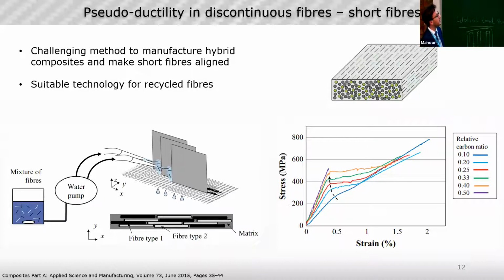The short fibers let us exploit the potential of the carbon, the stiffness of the carbon, which is very important, because with hybridization we can lose some performance of the carbon layer. But in this case, we can play a little bit with this grade of hybridization and try to exploit as much as we can the potential of the carbon and still have a pseudo-ductile effect. The only issue with this configuration is that it is quite challenging to create the layup and align the fibers.